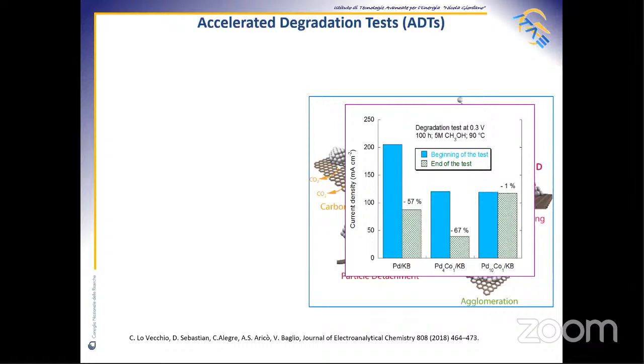The mechanisms causing a decrease of the catalyst performance are summarized into these points: dissolution of metal ions from small particles into the membrane, or redeposition onto larger particles, or corrosion of carbon support with the loss of electronic contact, or particle coalescence. Here, the degradation test at 0.3 volt in 5 molar methanol feeding showed that including a small amount of cobalt in the structure of palladium, like in palladium 10 cobalt 1, is beneficial for the durability.